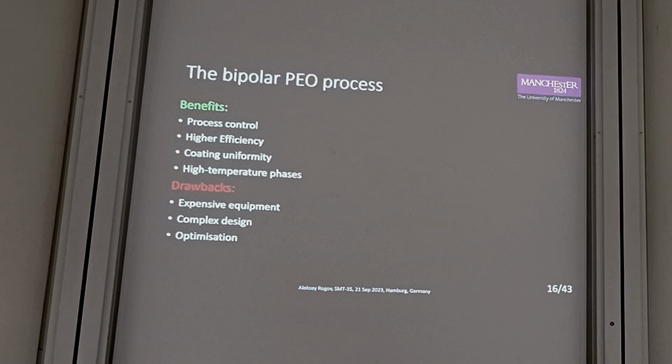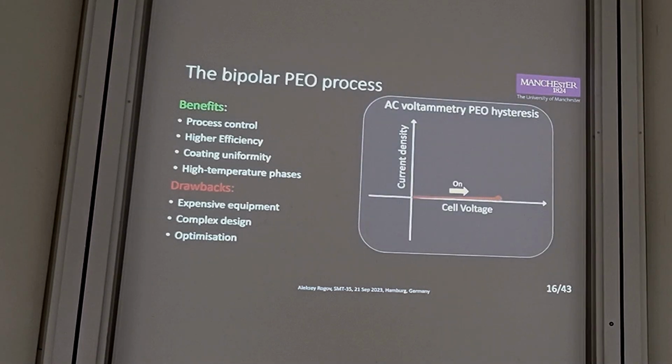We know that the bipolar PEO process has significant benefits such as better process control, higher energy efficiency, and better coating uniformity, and some drawbacks like more expensive equipment, complex design, and difficulties with optimization. However, there are some particular experimental features of this electrical mode.